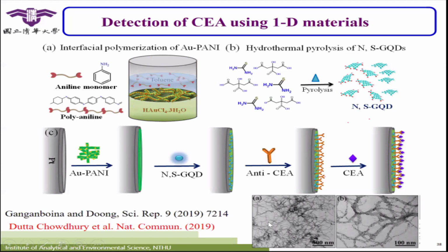When we enlarge this, we can see that this one is the polyaniline, quite good, one-dimensional. When you put the gold on the surface, you always see some spots here. These spots are the gold nanoparticles. Then we use this to put the NSGQD and the anti-CEA antibody on to detect the CEA.